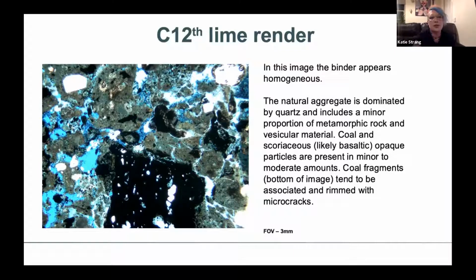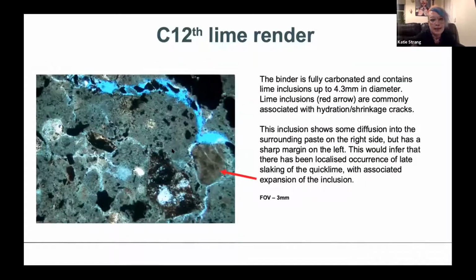And there's lots of cracks that are associated with these coal fragments. That can happen for a variety of reasons, but it's quite important to note because it does create porosity within your material. And in this image here, you can see a lime inclusion, which is highlighted by the red arrow. One of the main things that we're interested in with lime inclusions is their shape and their texture, and what that tells us about how the lime itself was made. So in this example, it's highlighted on the left-hand side, it's got quite a distinct margin where there's not much diffusion into the surrounding binder, whereas on this side, you can see it's got quite a diffuse margin.